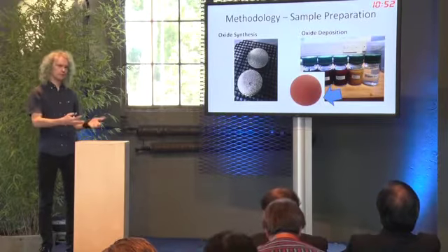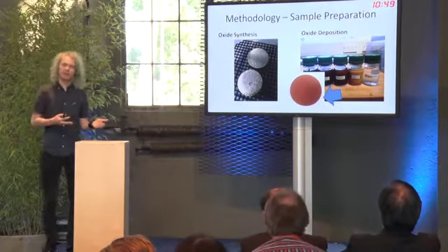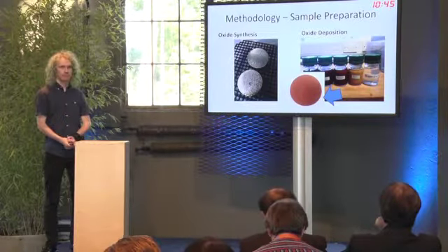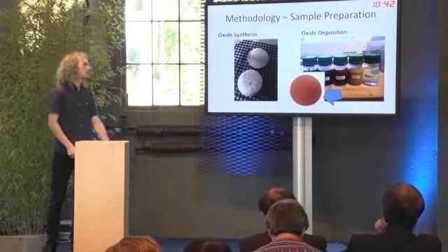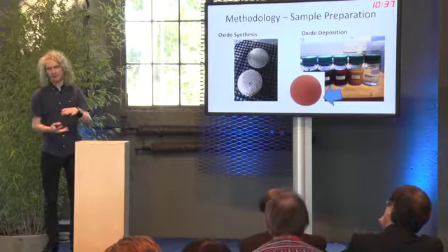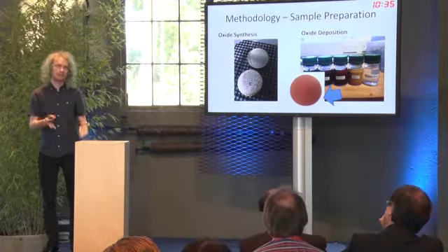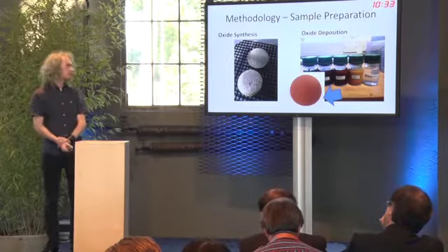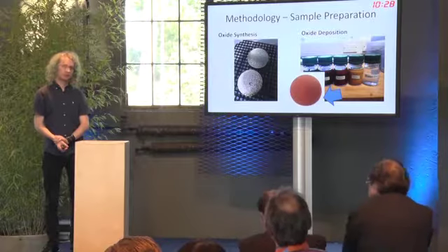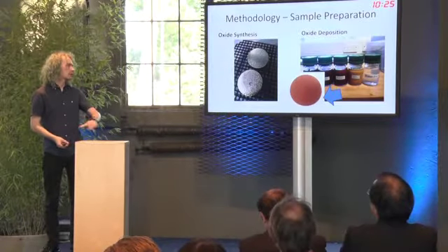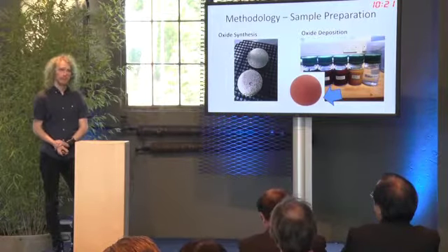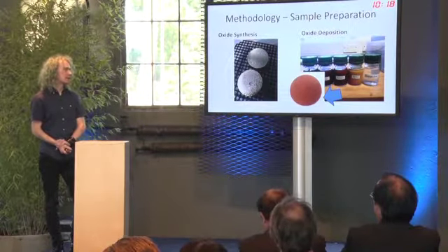So we took these conditions, and then we tried to replicate them in the lab by controlling the humidity and the temperature. So here are our steel samples that we've put into environmental chambers consisting of saturated salt solutions to imitate different changeable conditions. And secondly, what we did is we dropped oxides of specific individual types onto these steel samples as well, to see if we can run them through and figure out how the individual oxides are